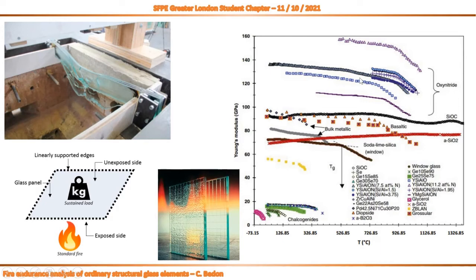So where is the problem for traditional glass? The problem is not only related to the very limited tensile resistance, as we discussed a few minutes ago, but also to the sensitivity of its elastic modulus to high temperature. In the figure on the right, you can see what I mean. For sure, there are several types of glass, but the traditional one we use for windows and building applications is the brown one. I don't know if you see my mouse, but okay, the brown in the bottom region of the chart is our reference mechanical parameter. In few words, we start from 70 gigapascal in cold conditions, and you see a linear decrease of this elastic modulus with temperature.